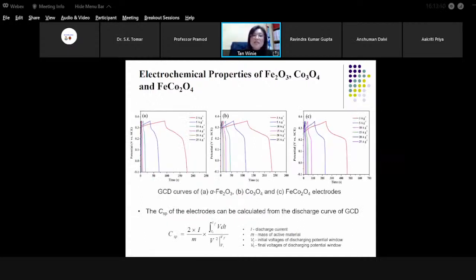So we did the GCD, the charge discharge curve. These figures demonstrate the GCD curves of these three materials. A is the hematite, B is the cobalt oxide, and C is the iron cobalt oxide at various current densities. We calculated the specific capacitance from the discharge curve of the GCD using these equations, where I here is the discharge current, M is the mass of the active material, VF and VI are the final and initial voltage of the discharge potential window.